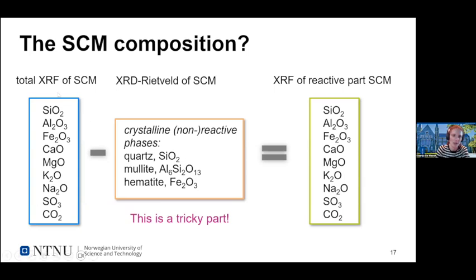You could use the entire XRF, so the total XRF of your SCM, but as Ruben earlier said, quite a bit of it can be crystalline and inert. So if you're able to quantify the crystalline non-reactive phases, just as examples, quartz, mullite, hematite, you could check the oxide compositions of these and subtract it from the total oxide composition of your SCM, and thereby obtain more an idea of what the composition of the reactive part of your SCM is. And then include this into your thermodynamic modeling, because that's actually what's going to go into the system. But this can be a bit challenging.